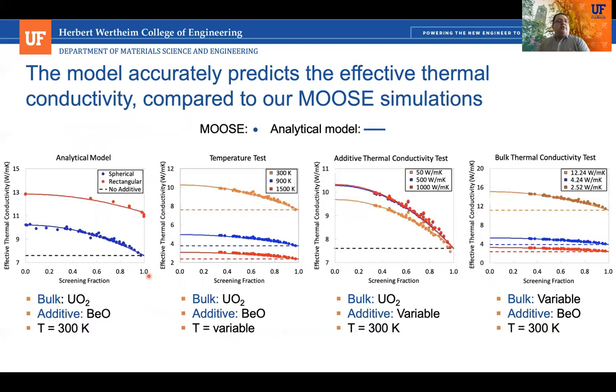So now let's look at how this model performs. This figure over here on the left is showing the comparison for all of the results that I've shown you previously. So this is with UO2 and BeO at 300 Kelvin, and for both the spherical and rectangular particles. And we get very good predictions. The model predicts very closely to what we got from the finite element method.